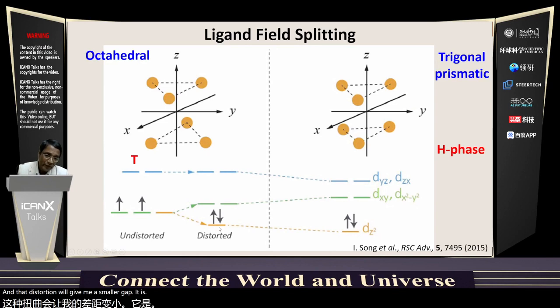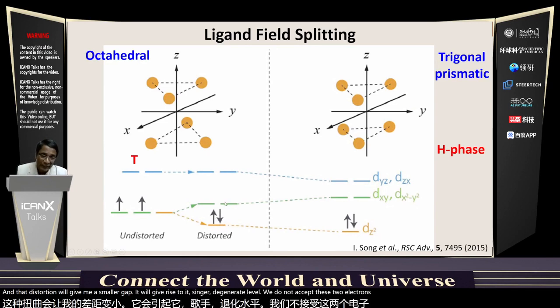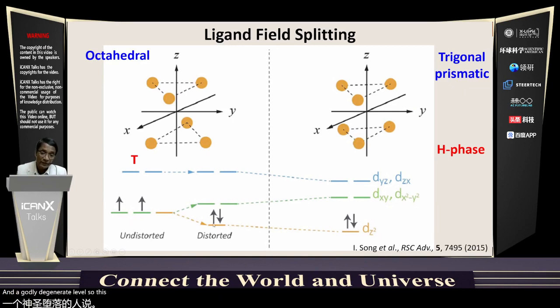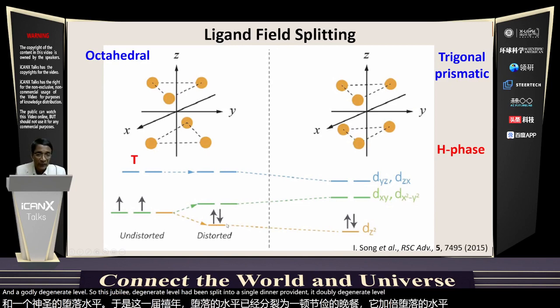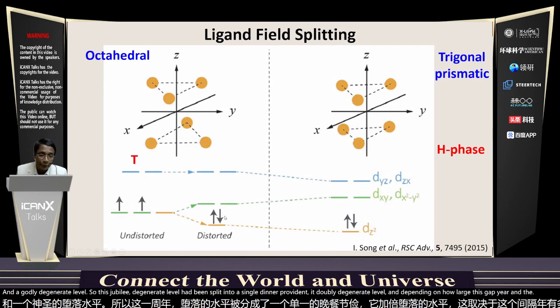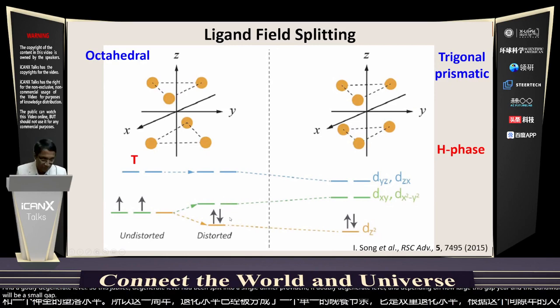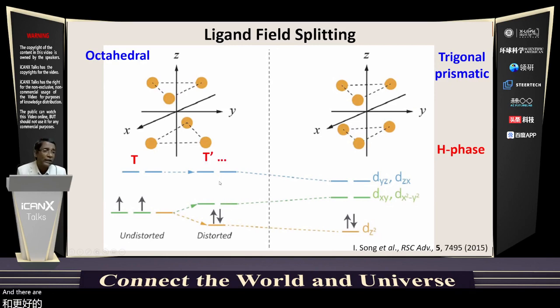It will give rise to a singly degenerate level, which will accept these 2 electrons, and a small gap and a doubly degenerate level. So this triply degenerate level will then split into a singly degenerate level and a doubly degenerate level. And depending on how large this gap is, and the bandwidth of this, if the bandwidth is smaller than the gap, then the system will be a small gap insulator. And there are different kinds of distortions possible, and they're written as T prime, T double prime, T triple prime.